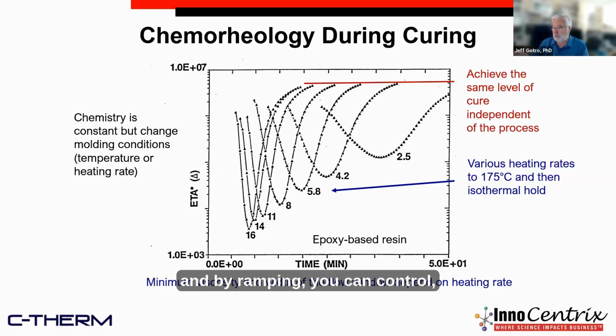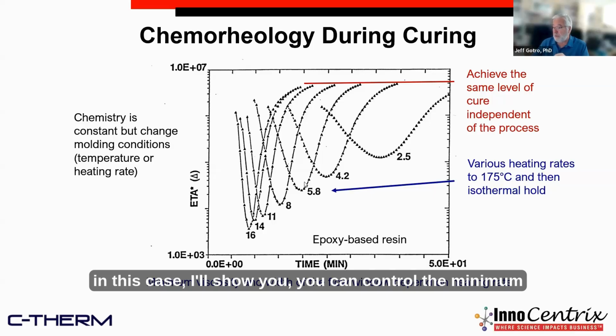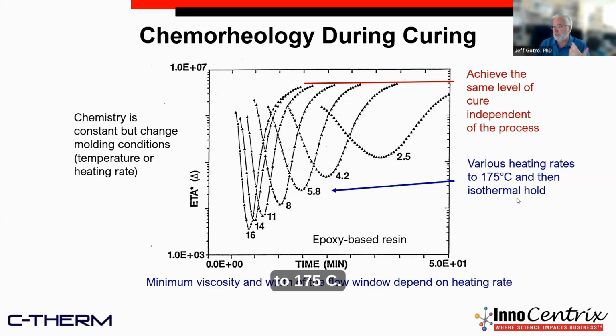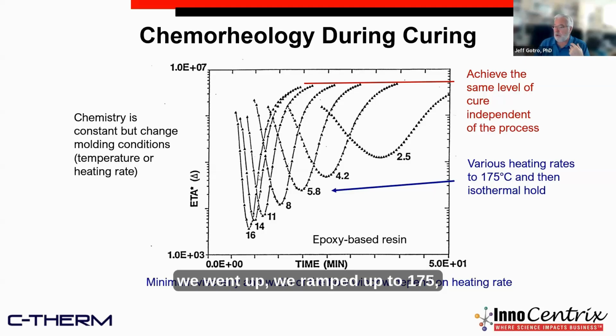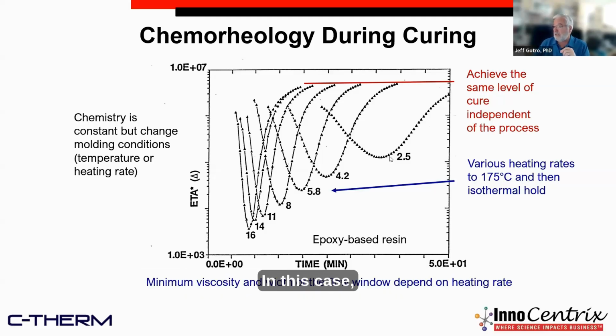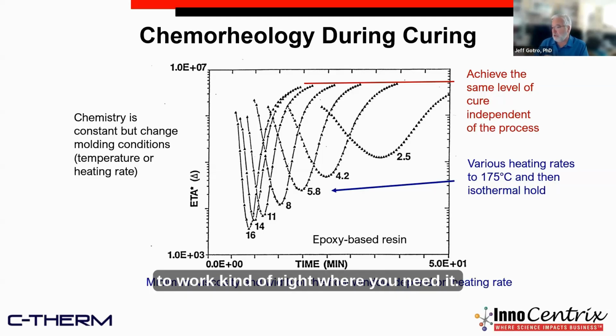And by ramping, you can control the minimum viscosity. The numbers along the bottom here are the heating rates to 175 C. So in this case, we started at room temperature, ramped up to 175, and then held it. You can see that if you ramp very quickly, you get a very low viscosity, but it cures really fast. So the viscosity may be really low and you can get it into the mold, but it may stop before it flows all the way in because it's curing too quickly. At a slow heating rate, the viscosity is very high, so it may not flow where you want it. So what the process engineers and the formulators work on is getting the process to work right where you need it.